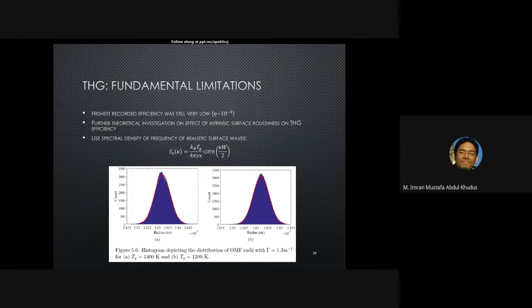And what we did was we looked at what the limiting factor is. We looked at the surface roughness of the optical microfiber itself. If you're pulling a fiber, it's glass. Glass has a large processing temperature. You've seen people play with glass before, I'm assuming. You can have glass which is fairly hot, but you can still shape it, right? Now, if you pull glass and then cool it immediately, the vibrations inside the glass get trapped, the phonons get trapped, and the trapping of these phonons constitutes the surface roughness, as it were, of the material itself.